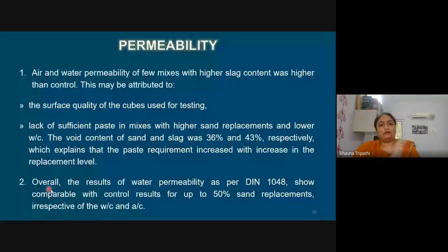Overall, what we can conclude is that for permeability, if we go by all the three kinds of tests, then we can recommend 50% replacement. However, if we can modify our mix to compensate for this, then we can go for 70% replacement also.